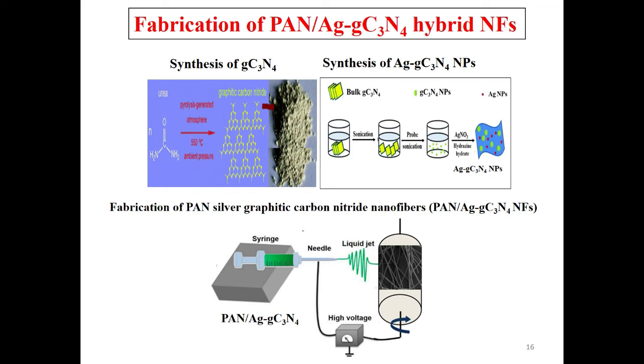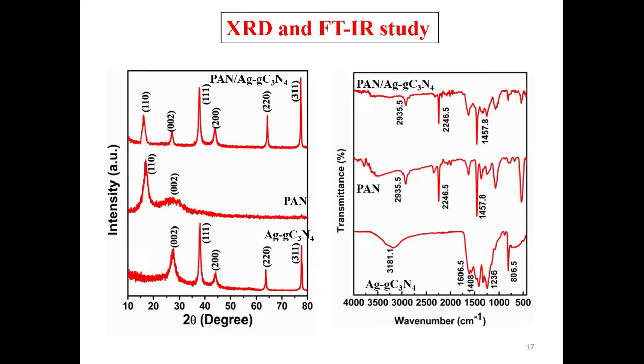It is not getting dissolved; it is getting dispersed into the dimethylformamide solution. A moderate viscosity solution of polyacrylonitrile is then mixed in and sonicated. The sonicated solution is then transferred into the syringe and sufficient voltage is applied, and the fibers are drawn with the help of the electrospinning technique.